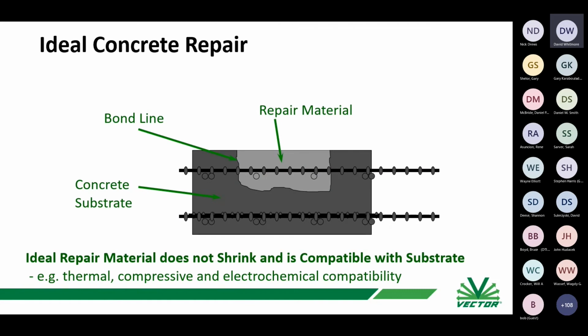Okay, so when you do a repair in a perfectly ideal world, we want that repair to be... If you look just below the graphic, the graphic's showing a repair in a piece of concrete. You've got two different shades of gray illustrated by the concrete and the repair material. And the first line of green underneath says the ideal repair material does not shrink. The repair doesn't shrink because that's going to create cracks at the edges or maybe cracks within the repair itself that obviously chlorides and whatever can get down in, and your service life will be very much shortened.